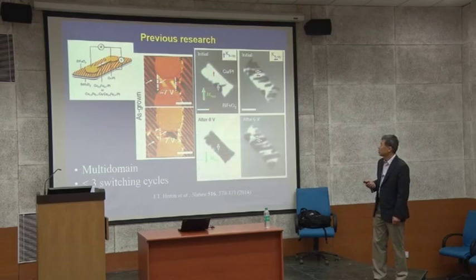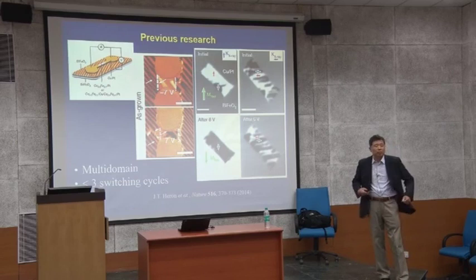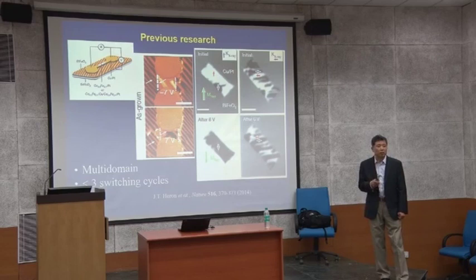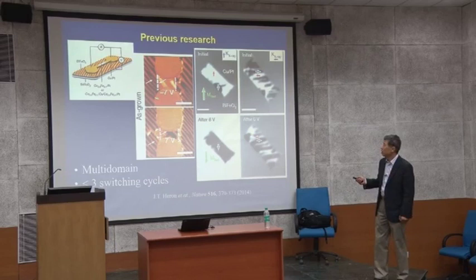Previously, this kind of work was done in the bismuth ferrite system. When you look at bismuth ferrite and its growth, you see different contrast in the PFM images. PFM is piezoresponse force microscopy, a scanning probe technique. You measure the piezo response, which reflects the polarization and its direction. So you can see that this region and that one are different domains.